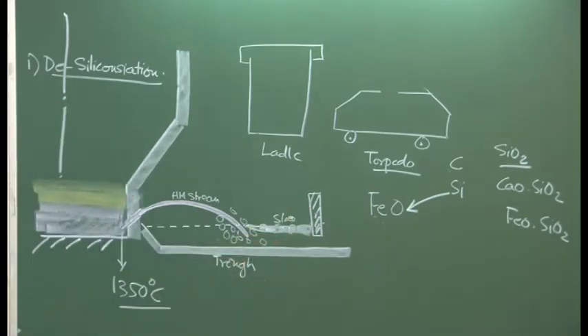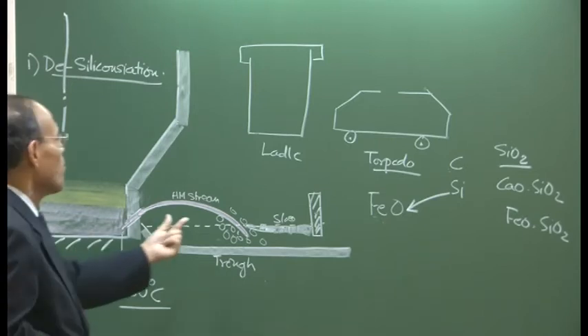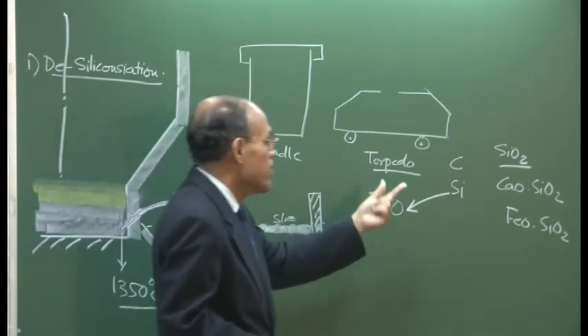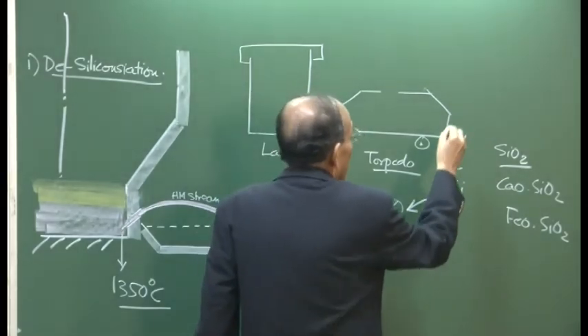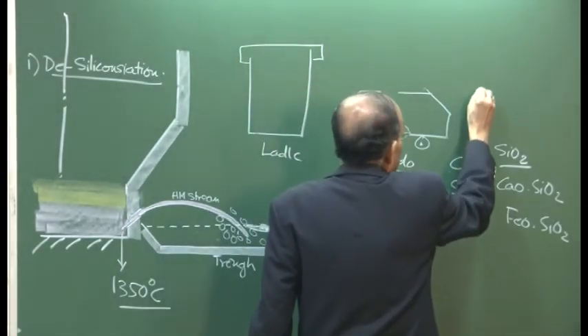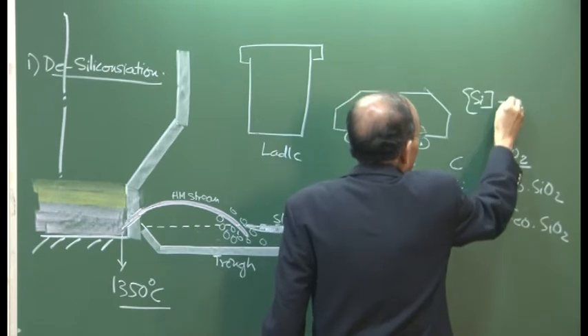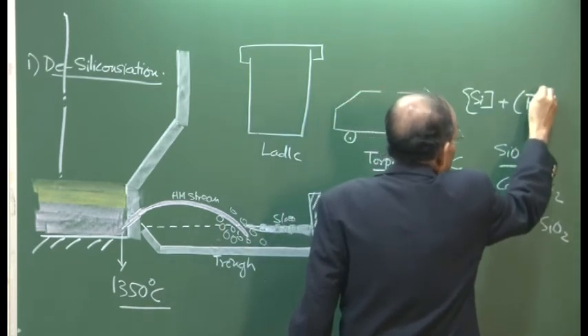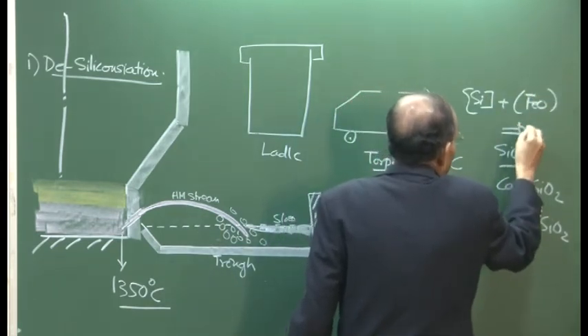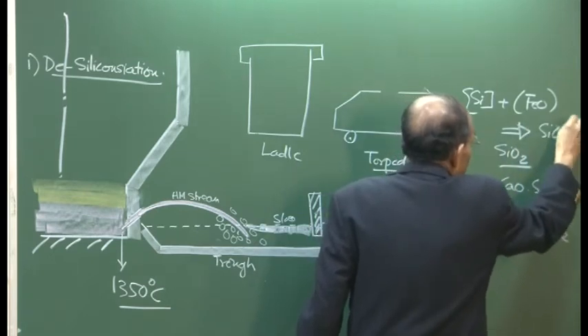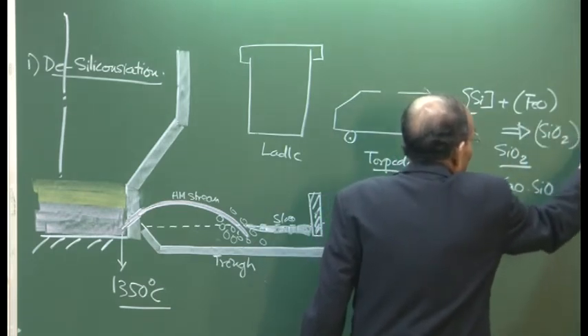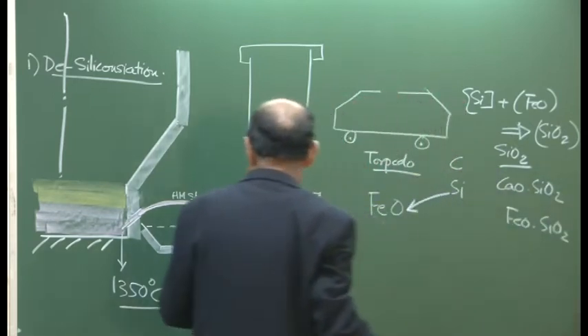So, it is straightforward, very simple, thermodynamically feasible, and the kinetic conditions are favorable here. These reactions, for example, if you have silicon dissolved in hot metal and FeO that you have added, because the oxide does not dissolve, it is again a slag-metal reaction, and the agitation is going to be very, very large. So, therefore, I can say that this is a favorable site.